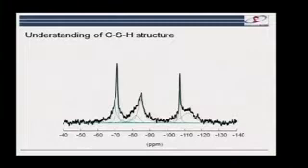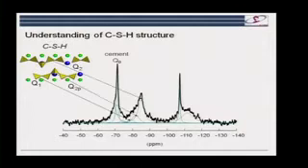This shows a typical spectrum from a concrete. You see this is quite a noisy spectrum. It can be deconvoluted into these peaks, and then these peaks can be associated with different groups. These groups down here are the Q0 groups coming from the cement that's not reacted. It's quite difficult to get this quantitatively, but you can pick out these Q2 groups, which are here.